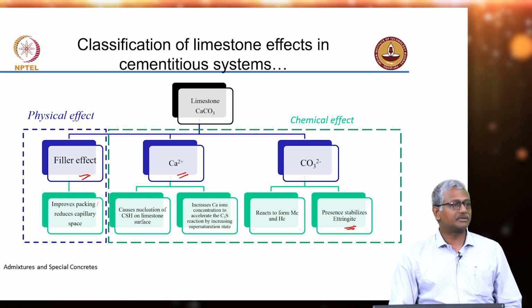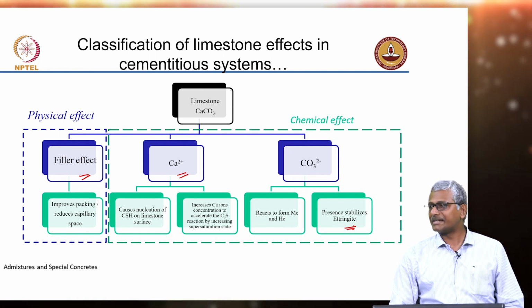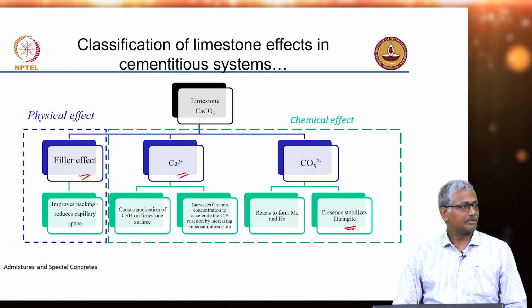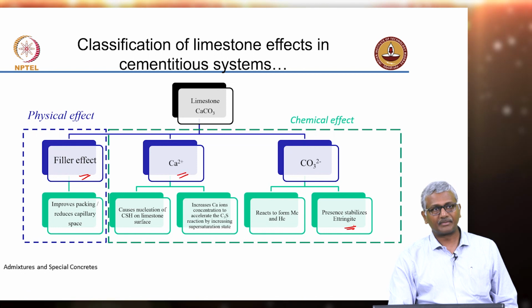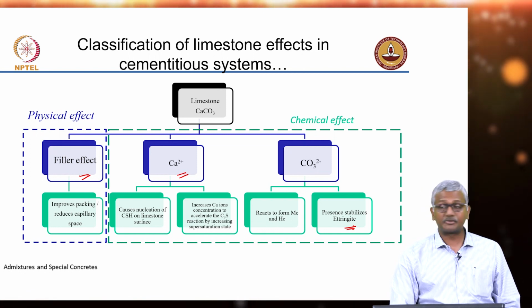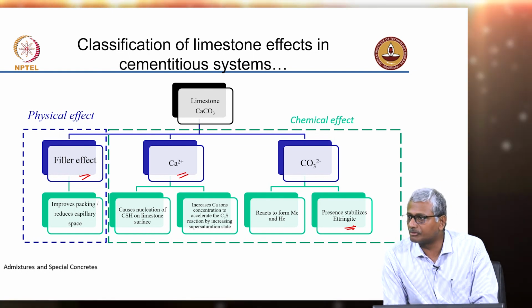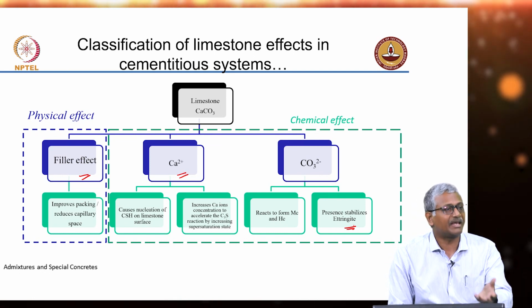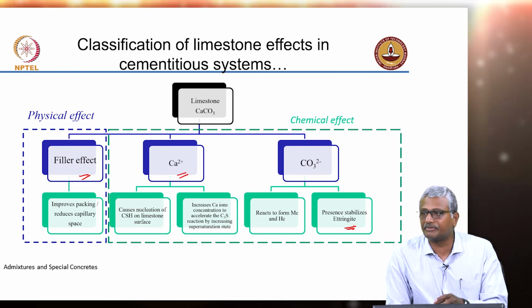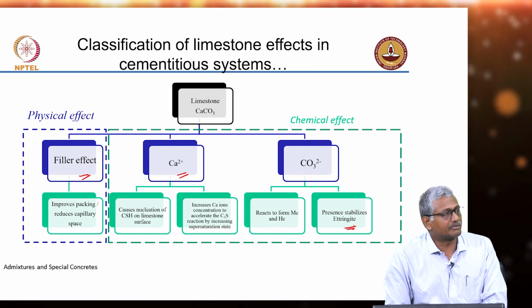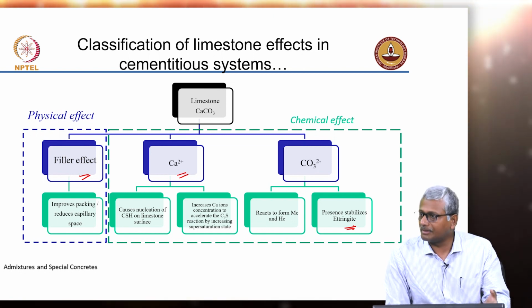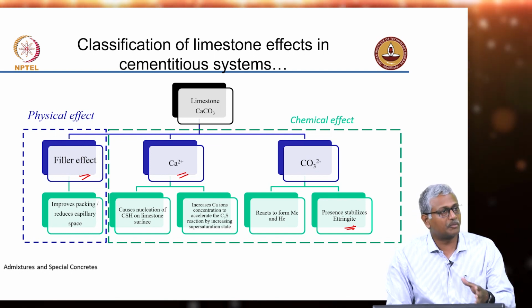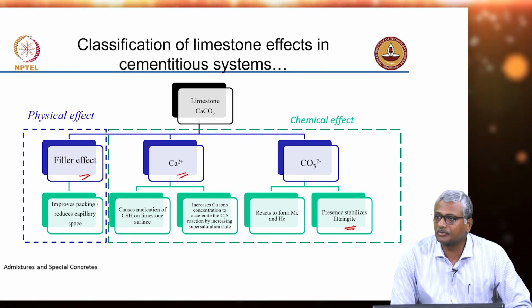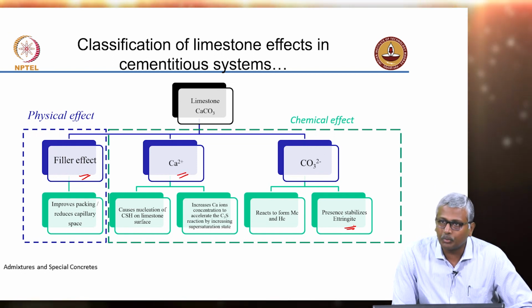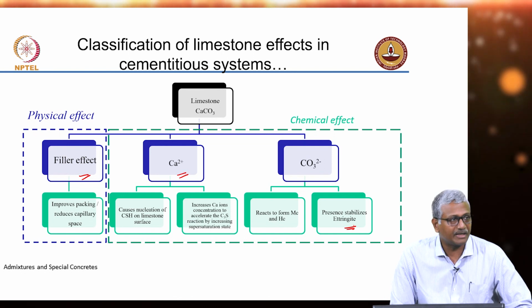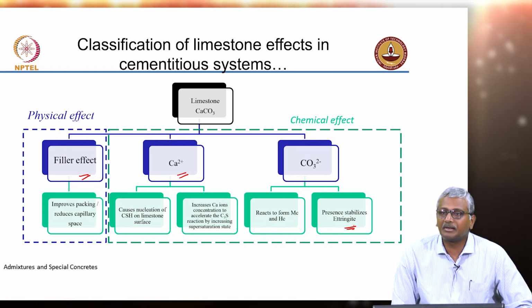Main thing is the reactivity of the limestone itself. Only a fraction of the calcite, and only if it is very fine sized, okay, will dissolve and be available for reaction. So you're not going to be able to have a large quantity available. So in the use of limestone as a performance improver, 5% is used. So there's not enough limestone available to give enough reactive carbonate in your system. If you put 10 or 15%, you are increasing the chance that there's more reactive carbonate available in your system, right? And by providing an aluminosilicate like fly ash or slag or calcined clay, you give additional alumina which is reactive to combine with the carbonate in the system. So there are obvious benefits which you cannot get by plain Portland cement or even Portland limestone cement. So that's where you can actually harness that benefit in the case of your ternary blended systems.